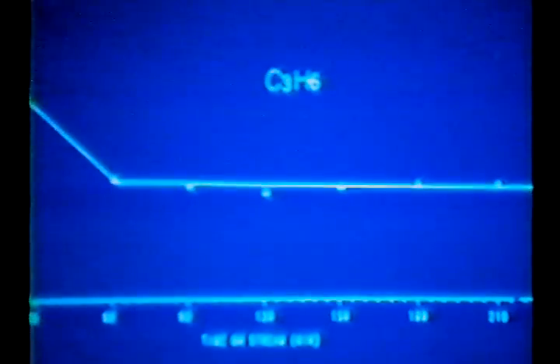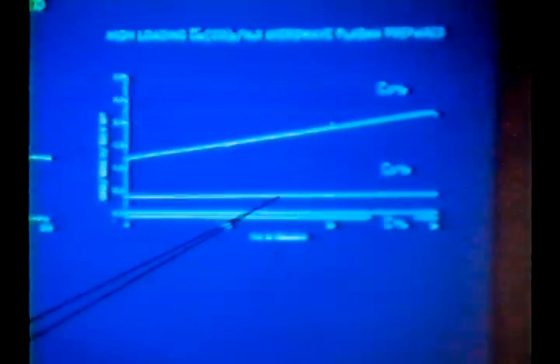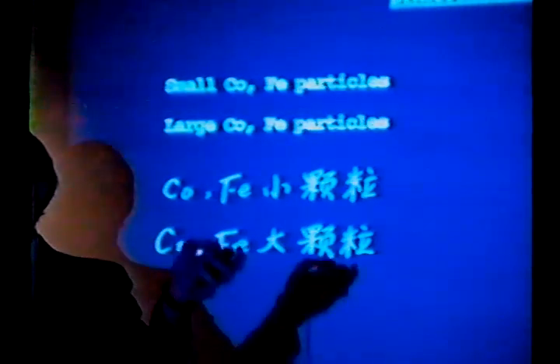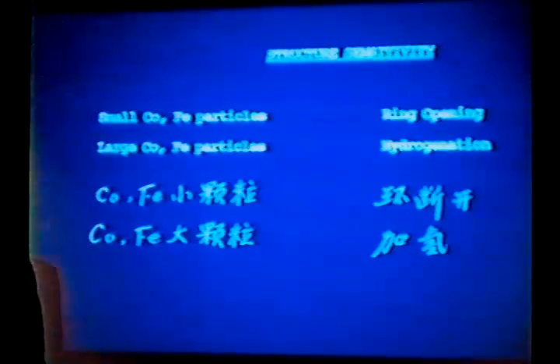What do we observe? With the small particles, low loading of cobalt in the microwave plasma, at low temperature we see propylene. We only see ring opening. And we see a fairly low turnover frequency as well. But with a high loading, we start to see methane and ethane. We also see propane as well as propylene. Or if we take the small particles and purposely sinter them at 160 and grow them in stages, what we see is first ring opening, and then hydrogenation, and then cracking. In general, the small particles at low temperature catalyze ring opening reactions, and large particles catalyze hydrogenation and hydrogenolysis reactions.